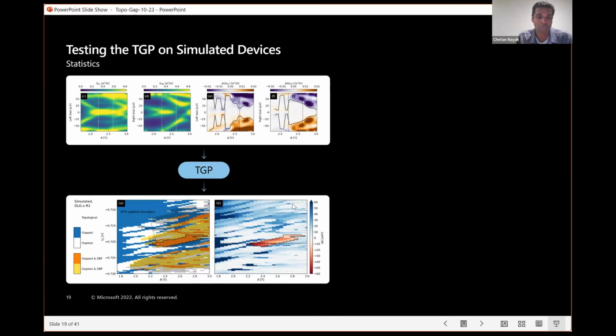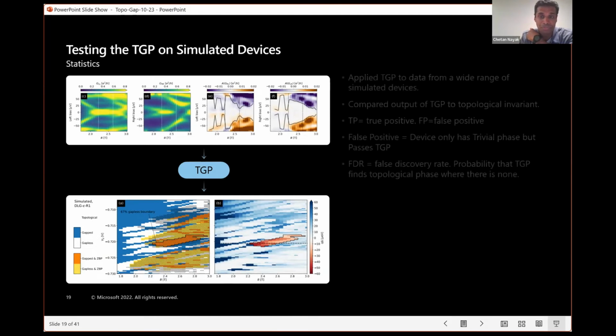And what we see is, with this simulated data, the topological gap protocol finds a topological phase over here. There's lots of sort of small gap or gapless regions out here. The trivial regions are out here where it's a gap trivial superconductor. And what you can see is what the TGP identified. This color scale shows how large the gap is, and what you can see is this identified topological region actually does have scattering invariant equal -1. Okay, so it's in fact in the topological phase by that measure.